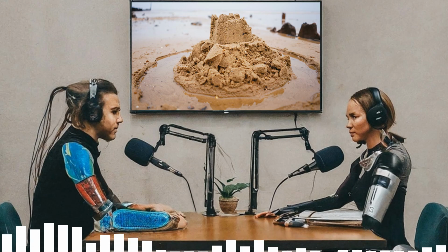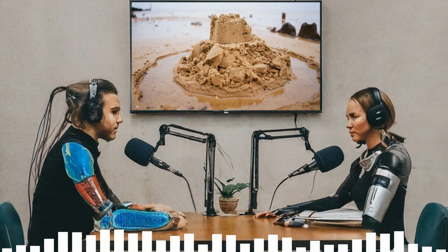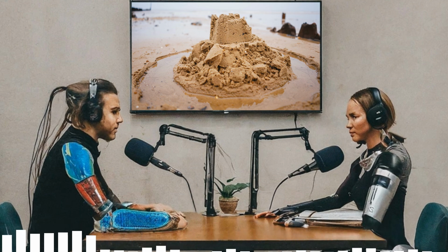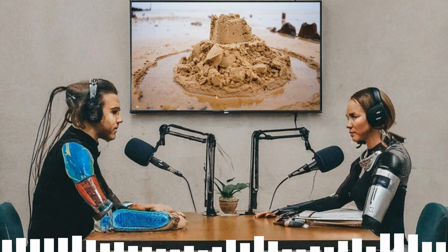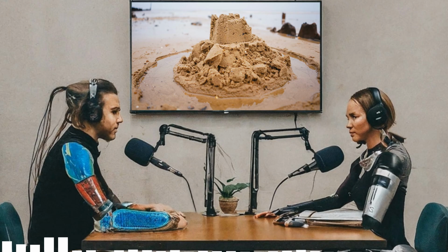Yes, the dreaded mushy collapse. I know it well. And the researchers actually built little sandcastles to test this. They used regular beach sand, mixed it carefully with water, put it in PVC pipes, and compacted it. They mentioned dropping a thumper like 70 times for each layer. That's serious compaction. Yeah. Then they pulled the pipes away.